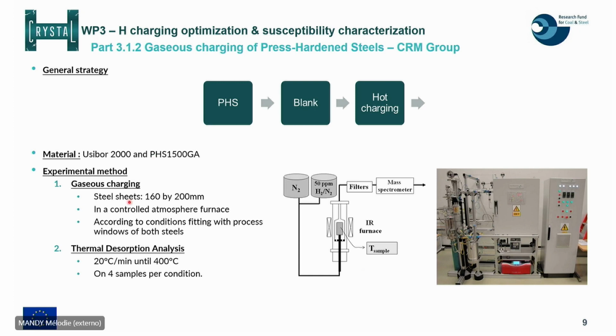And after gaseous charging, we perform the thermal desorption analysis. So thermal desorption analysis, in what does it consist? We put the sample in a furnace. We heat the sample at a given rate. Here it was 20 degrees Celsius per minute until a temperature of 400 degrees. By doing this, we let hydrogen that was absorbed in the material desorb, and it will be carried away by nitrogen, which is an inert carrier gas here, until a mass spectrometer to be quantified. Here you see just a small picture of the equipment.